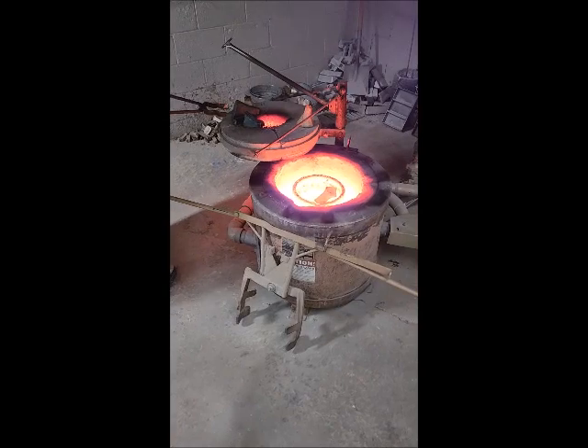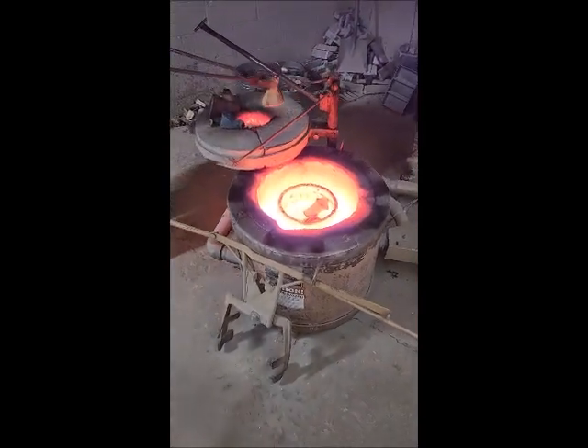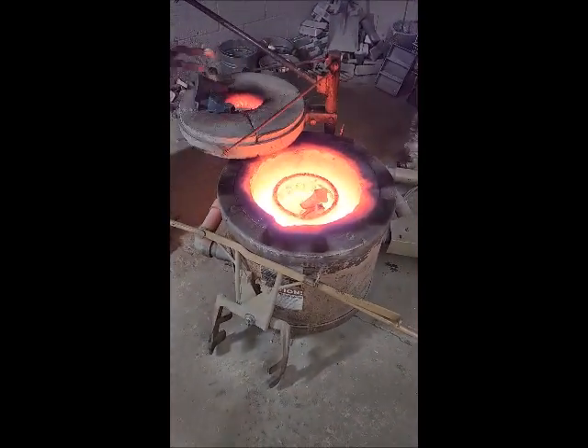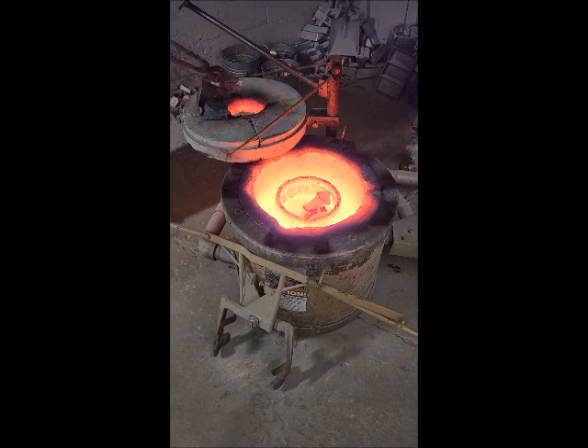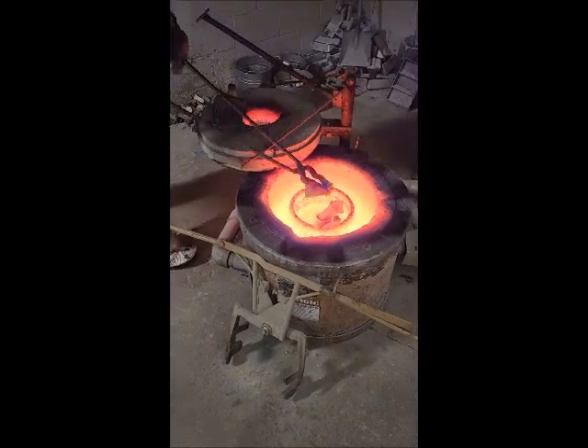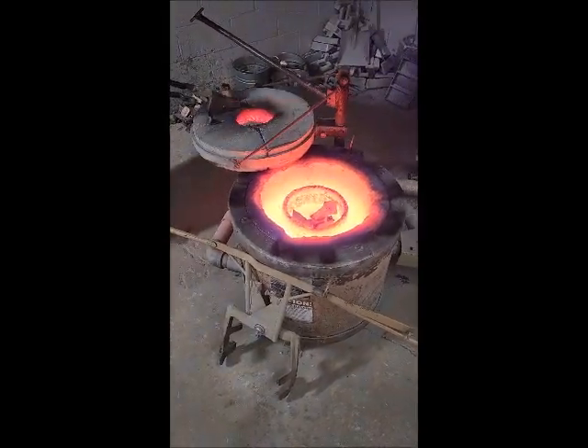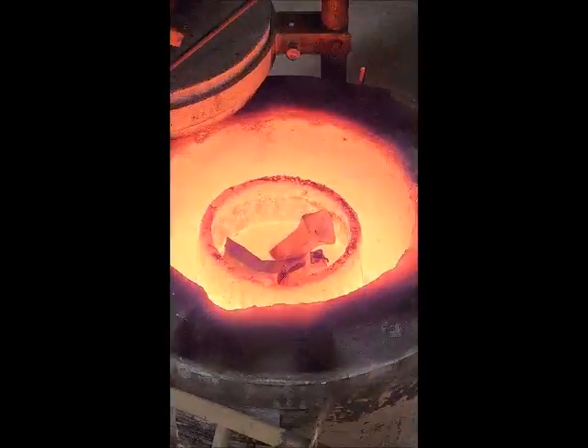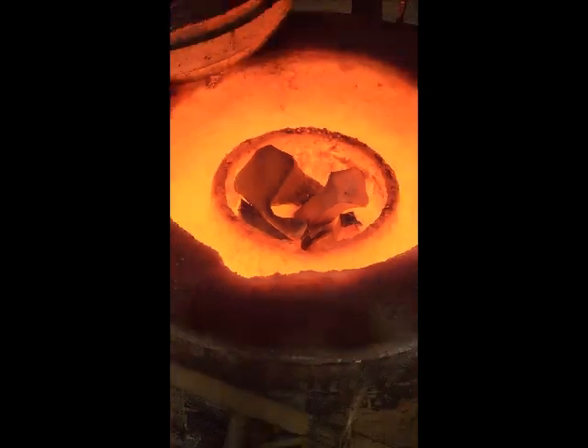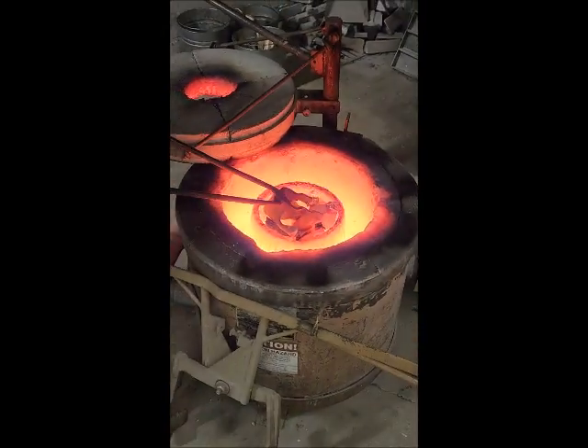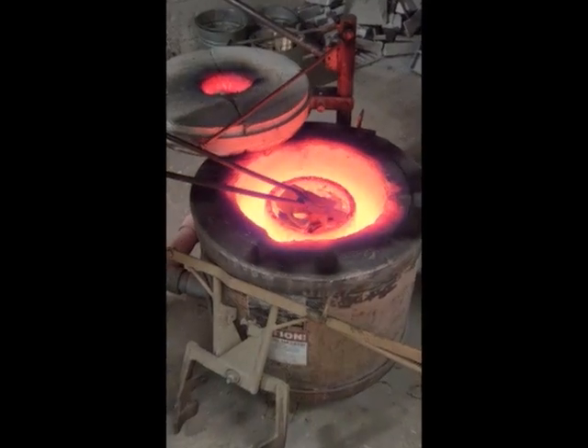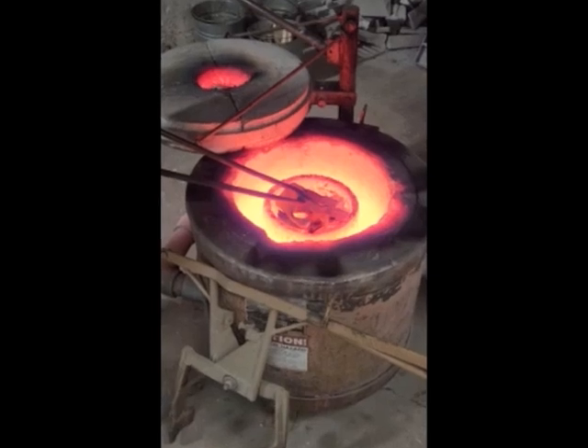The ceramic shell is then returned to the kiln and is heated to 1,650 degrees Fahrenheit. Reheating the shell prevents it from cracking when molten bronze is poured into the shell and also aids in the flow of molten bronze. While the ceramic shell is reaching the correct temperature in the kiln, solid bronze metal is placed in a crucible and is heated to 2,060 degrees Fahrenheit in a melting furnace until the bronze becomes molten.